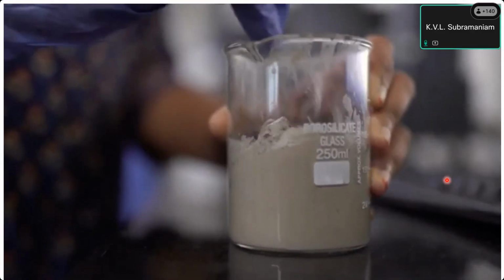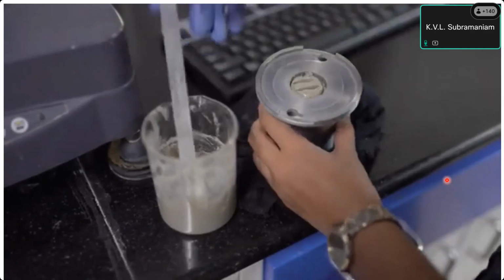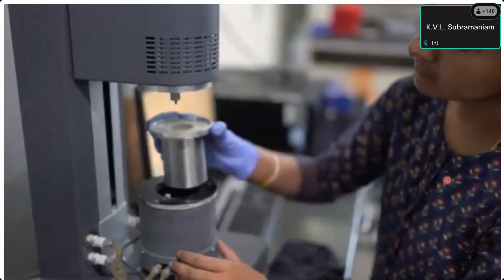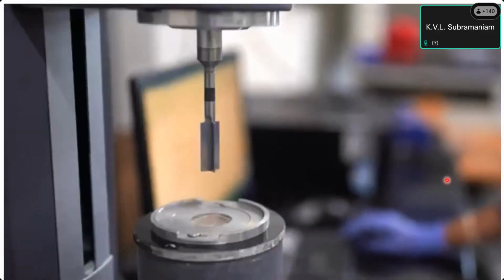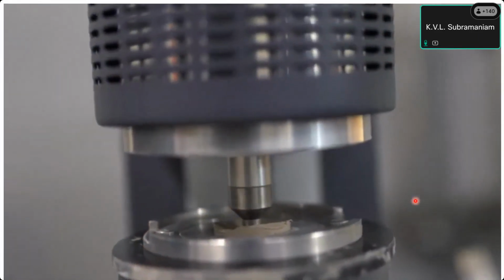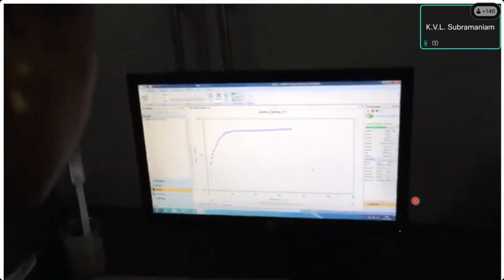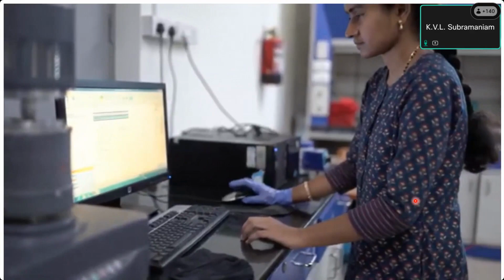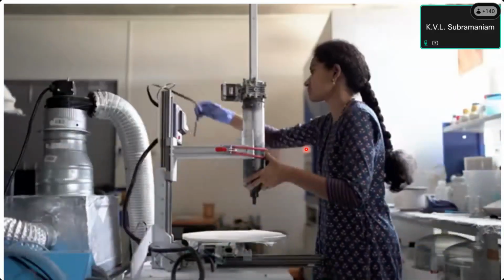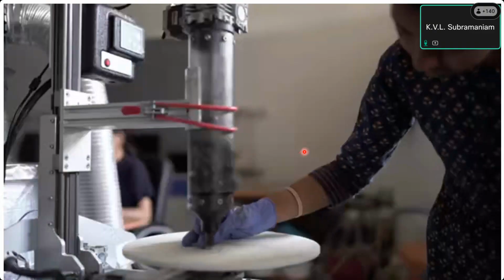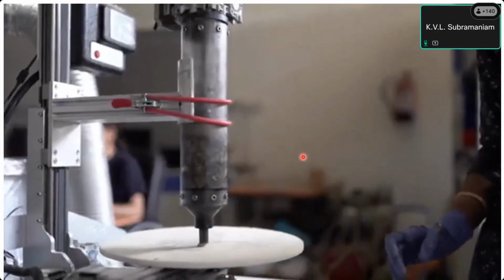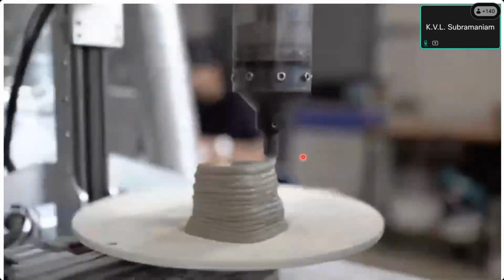So the rheology requirements for a printable material or a printable paste would be a high yield stress, low viscosity, and an adequate thixotropy. When it comes to concrete, the important parameters would be particle size distribution and volume fraction of the aggregate, and then the packing of the material. So only when all of these properties are engineered properly, a 3D printable material can be achieved.